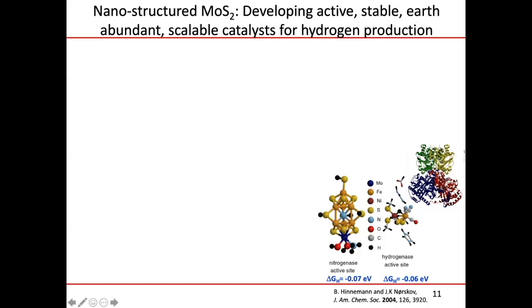And here's hydrogenase and nitrogenase, which are very good natural enzymes for producing hydrogen. You can see here they're every bit as good as platinum, but there's no precious metals in sight. And so thanks to calculations done by Bjørk Hinnemann and Jens Nørskov some years ago, they really tried to understand what makes these things tick. The long story short is that the motif you see here, which is an undercoordinated sulfur, behaves very differently and is far more active a catalyst in the enzyme than, say, the sulfurs up here that are coordinated to three metal atoms.